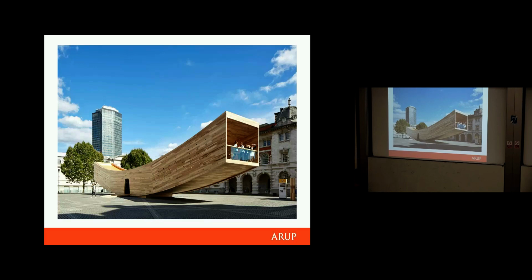That is why, if you had a 1 metre deep glulam beam, you wouldn't put a 1 metre deep plate in the middle of it, bolted to it, because as the wood tries to dry and shrink, the plate is going to restrain its shrinkage, and the wood will simply split because it can't deal with it. So the trick is that everything happens across the grain, and what you do is keep your steel plates quite small. If you look at a steel moment connection on a big member, you'll have a plate at the top for the compression or tension, a plate at the bottom for the compression, and a plate in the middle to carry the shear, but the three plates won't be joined to each other, so that the wood can easily move, shrink and swell across the grain.